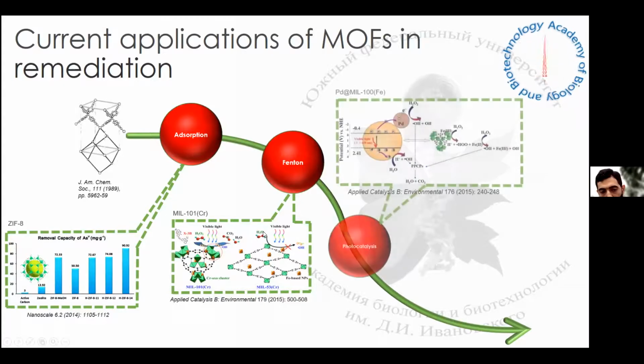The third example is a photocatalytic reaction, where we should have a tuned structure of metal-organic framework. Usually MIL, again based on iron, is used, but we should use some trace element to adjust the band gap so they can be activated by lower photon energy. Then they start producing hydroxyl radical by oxidation of the water molecule, then superoxide anion radical at the top of the conduction band, and then start targeting different organic pollutants.